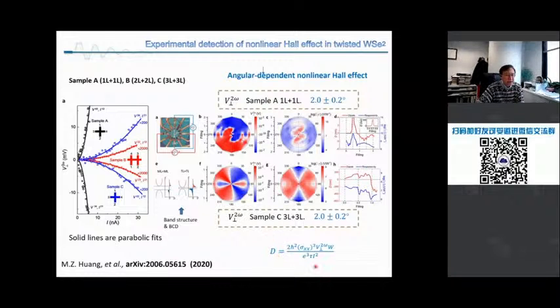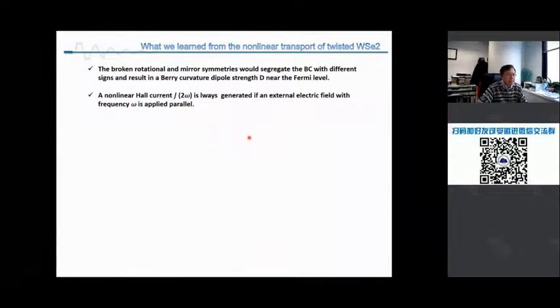Yeah. And the Berry curvature dipole can be experimentally measured if you know some parameters. The voltage that we measured, the sample width we know, the conductivity or resistivity, and the current, and tau is a relaxation time, which can only be estimated. And then we measure the Berry curvature dipole. At certain filling, you get a maximum. At certain filling, you get a minimum. This axis is the filling, and the color means the intensity. All right. So what do we learn from this experiment?